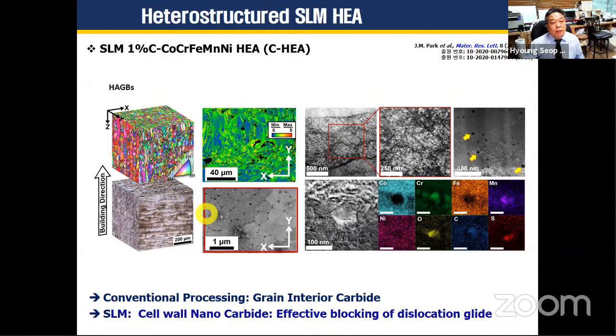It's not shown here. But on the other hand, as you can see here, the SLM processed carbon-added high entropy alloy produces cell wall nanocarbide. This black one is nanocarbide. It's only in cell wall and grain boundary as well, which effectively blocks dislocation glide, enhancing strain hardening, uniform elongation, dislocation density, and finally, ultimate tensile strength.